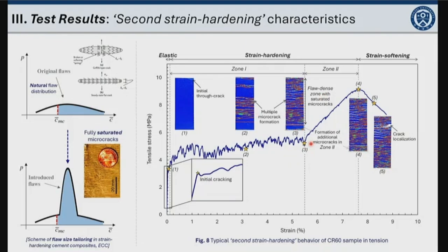However, after this point, the tensile stress starts to re-increase with the formation of additional cracks in this zone with only few or insufficient amount of crumb rubber. Once it reaches the bridging strength of the polyethylene fibers and the crumb rubber, the tensile softening behavior with crack localization was observed. Therefore, this second strain hardening behavior is caused by the insufficient dispersion of the crumb rubber.